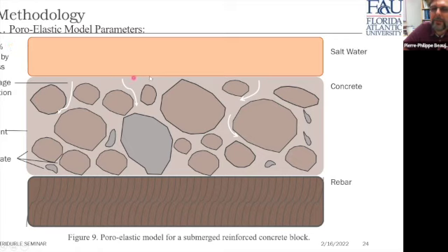So we assume that we have a water volume made of salt water with 10% of salt by unit of mass. And we actually model the reinforced concrete as the concrete, which is going to be a combination of aggregate and cement, where there are areas where seepage can actually take place. This is where the fluid can actually seep. And below that is the rebar. And as chloride reaches the rebar, corrosion starts taking place. This is the model we use.